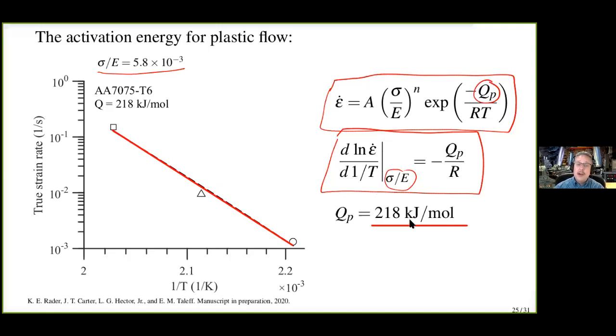This is much higher than we got for retrogression. Of course, it's a different process. It's also much higher than we would get for high temperature creep. This tells us that some different physics are going on, something we don't quite understand yet. I tend to think that what's happening is we have an activation energy for the cutting of some of the coarser precipitates that are left after the retrogression process has already proceeded.